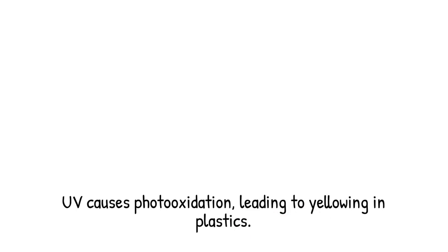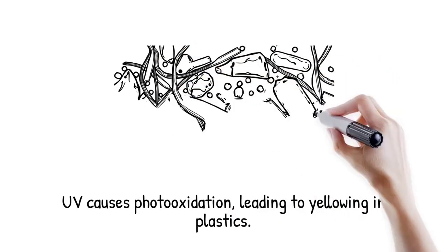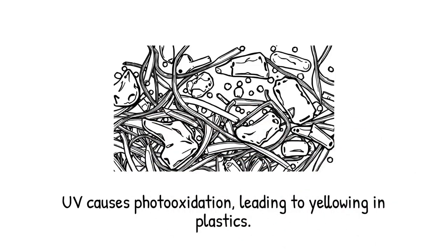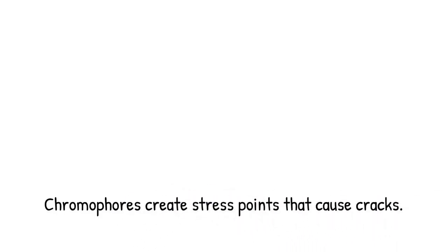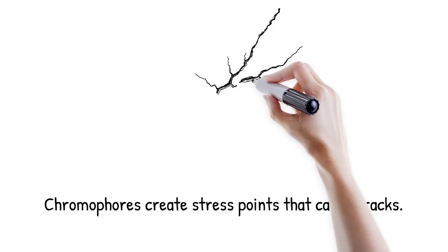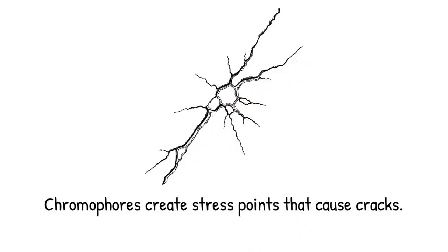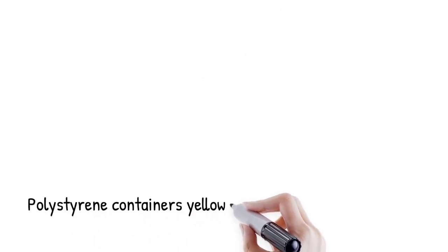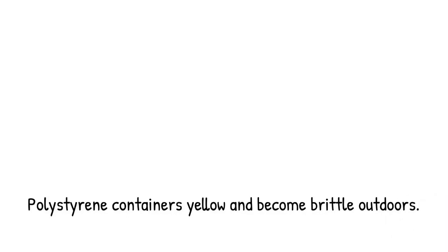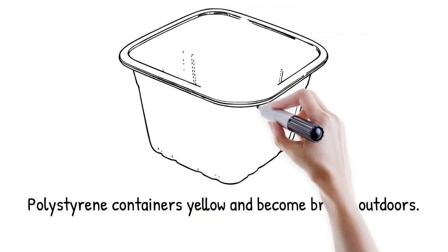UV exposure often leads to photooxidation, where free radicals react with atmospheric oxygen to form carbonyl and hydroperoxide groups, known as chromophores. These new groups absorb visible light, causing yellowing and loss of transparency in plastics like polystyrene. Chromophore formation also creates stress concentration points that nucleate cracks under mechanical load. The accumulation of oxidized moieties thus both weakens and discolors the polymer. Controlling oxygen diffusion and radical concentration is key to mitigating these effects. Clear polystyrene food containers turn yellow and become brittle after prolonged outdoor storage.